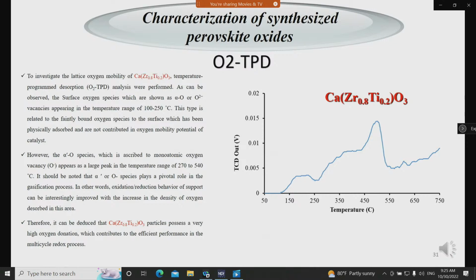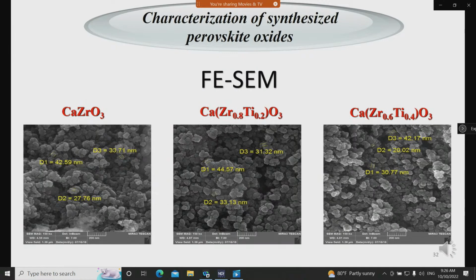And for the oxygen vacancies, we performed O2 TPD. The large peak of the O2 TPD may imply that this catalyst has high oxygen mobility. This can contribute to efficient coke removal in multi-cycle redox processes. The SEM image corresponding to the perovskite shows a spherical morphology, which can positively affect the homogeneous and uniform distribution of the active metal and prevent the sintering and agglomeration of nickel by proper interaction with the active metal, along with improving the active metal dispersion and enhancing the activity and stability of the catalyst.